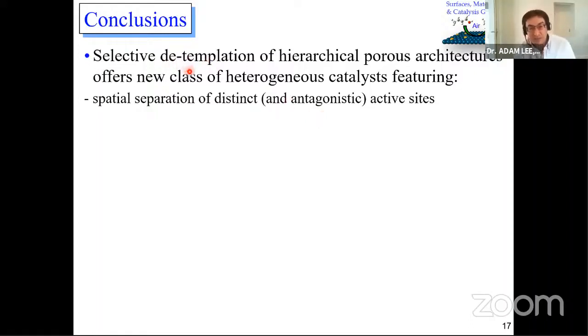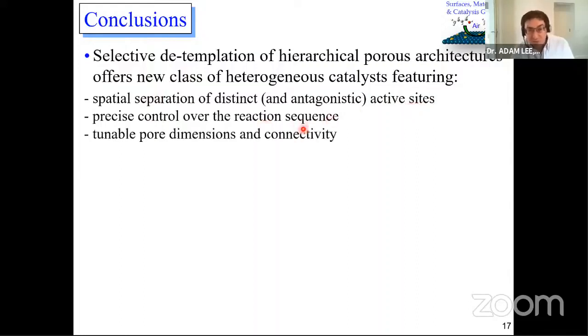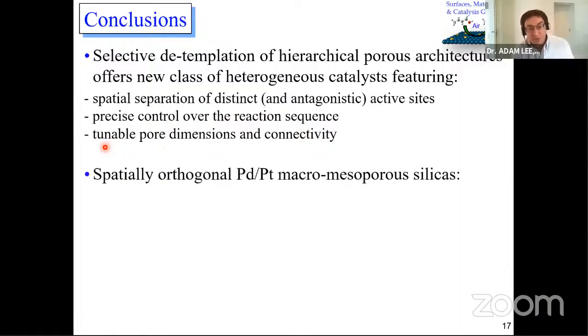Normally both templates are taken out together. We've done it one step at a time, and that allows us to put different active sites into different parts of the particle. And that's important because it now gives us very precise control over the sequence of reactions in cascades. I haven't mentioned this, but just to be aware that all of the pore properties, so the pore sizes, the size of the macropores, hundreds of nanometers, mesopores, 5 nanometers, and the way they connect to each other, whether it's 2-dimensional connections or 3-dimensional connections, all of those can be controlled. So we can tune all of the pore structures to make the pores bigger or smaller, etc., to control the size of molecules that can access them.